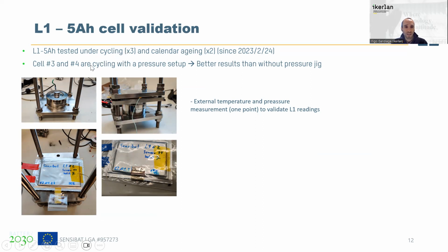Two of the cells that are cycling, we test them with a pressure setup. So they are under pressure, but not only under pressure, we are also measuring the pressure that the cell puts on to the outside. So like that, we tried to validate the information that we are obtaining from the sensor. So we have like a double check. We are obtaining the information from the sensor, and we are also obtaining it from the outside of the cell. And the same for the temperature. In both cases, from the outside, we were only able to measure it in 1 point instead of the 35 points that we are able to measure inside the cell.